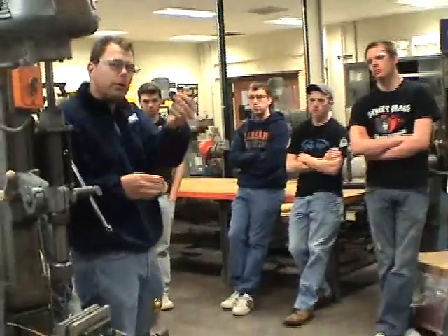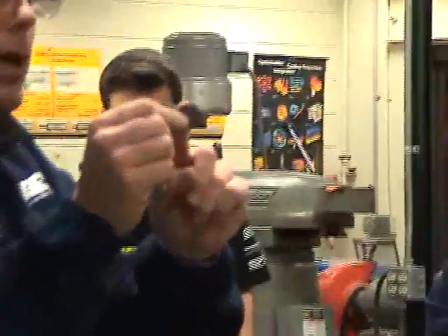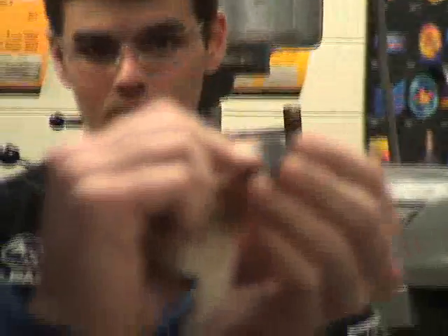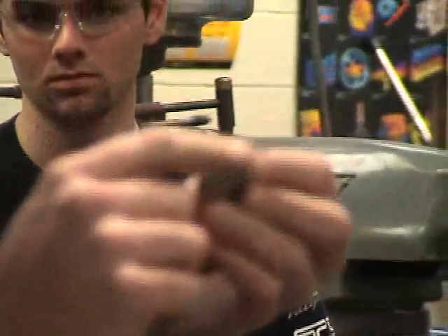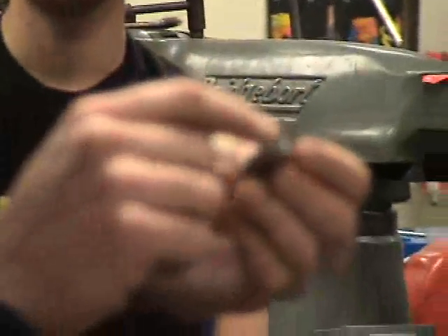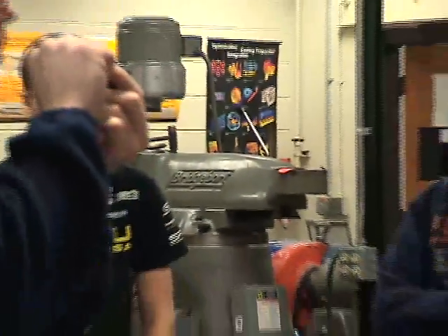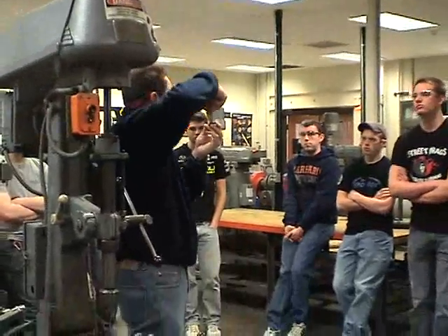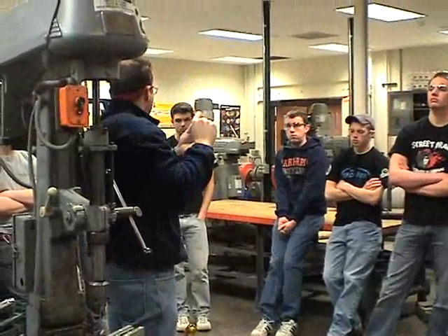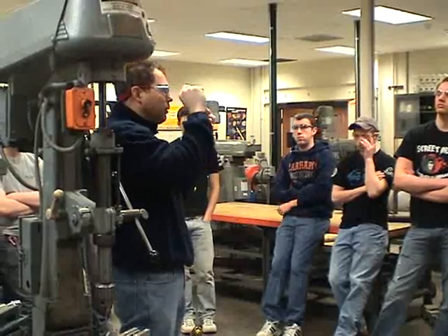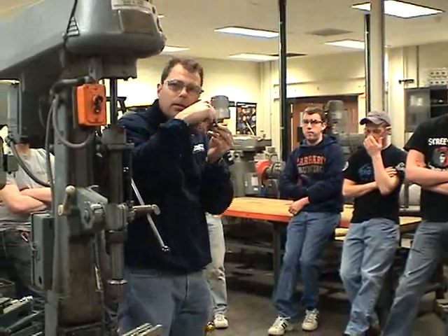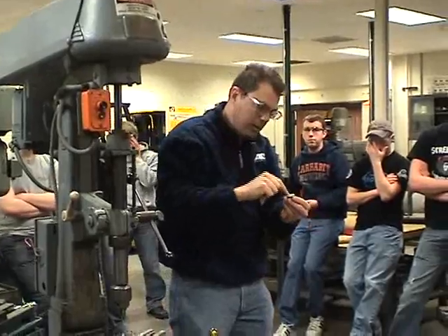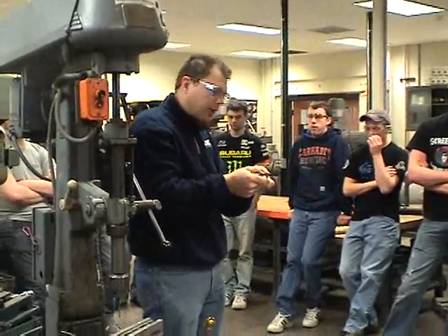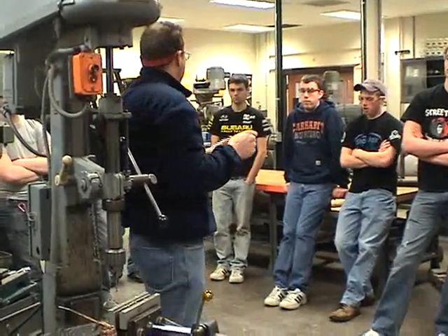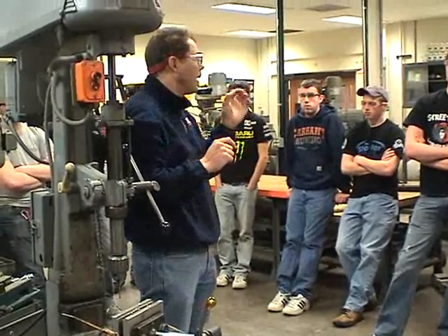Now we have a hole through it, and that hole will have a burr on the top and the bottom, as well as where we cut it off before. The problem is that when we take the first initial hardness, if there's a burr on there, the hardness tester puts 300 kilograms on the sample, on a little bitty indenter. And we're measuring a small movement in the depth, a small movement in that indenter. If there's a little edge that can get crushed, it will likely get crushed, and your hardness will be thrown off really badly that way.